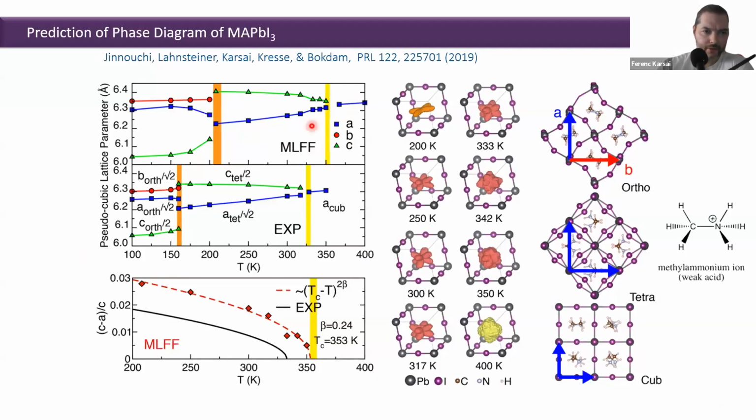This shows force field calculations, and this shows experiment. The first nice thing was that by just running a temperature ramped calculation, we could observe the phase transformation naturally. This is a big thing because usually if you run an MD, and it's not always the case, for example, I tried with magnesium oxide from the B1 to the B2 phase, it never happens. If you want to run MD and you want to see the phase transition appear naturally, it's not possible. You will need some kind of advanced molecular dynamics methods.